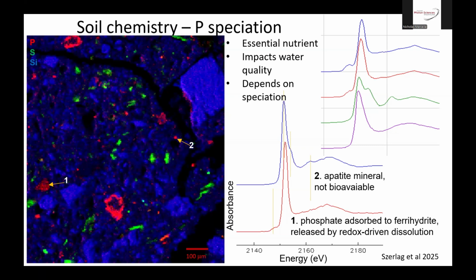No, we would typically map a large area at 5 or 10 micron resolution. Then regions that were more interesting, we'd map at 2 to 4 micron resolution, get more detail, and then go into places within that map to get point spectra. You have to go back to do the mapping at an energy above all 3 elements, and then do the XANES at an individual pixel of the map by scanning the energy. We've tried a couple of cases where you scan the energy and get a spectrum at every pixel. It takes forever, and you get a lot of spectra of things that you don't want. So it's much more effective and efficient to map the hot spots and then do the point spectra.